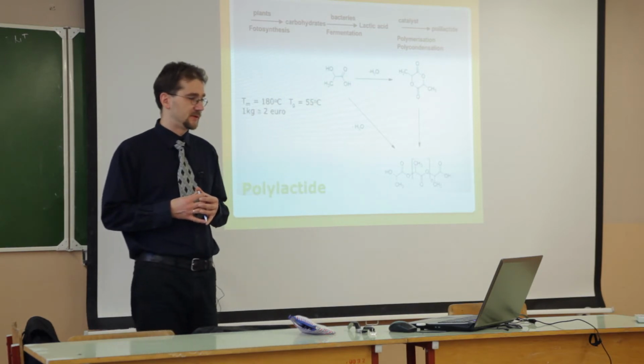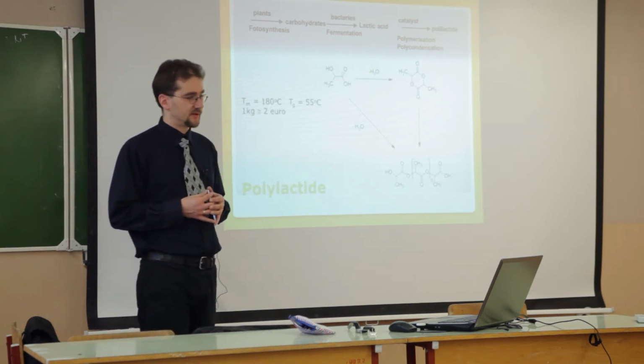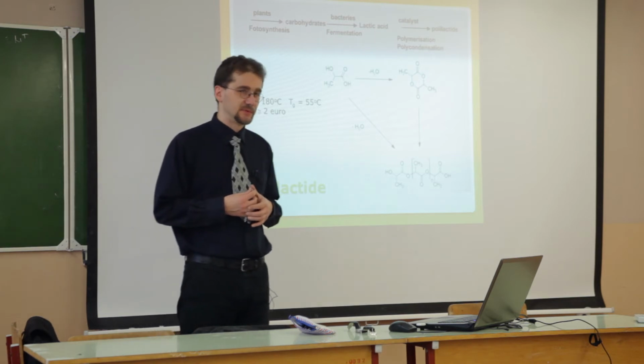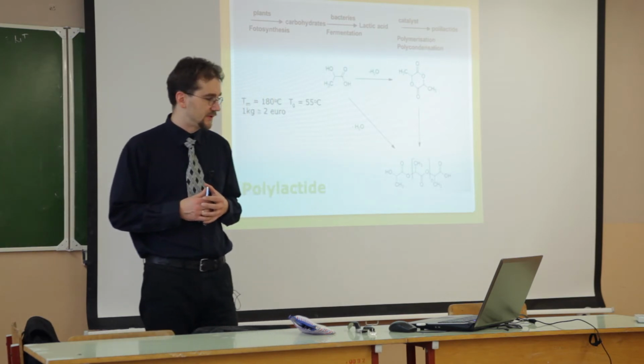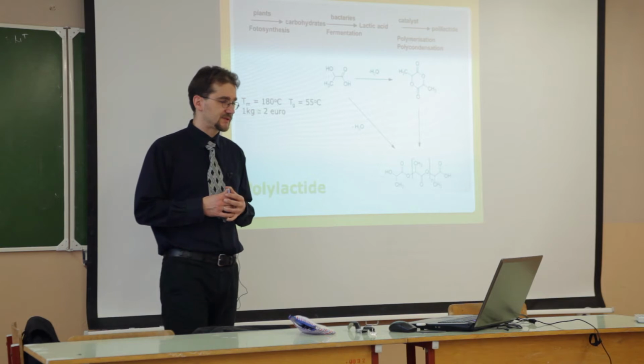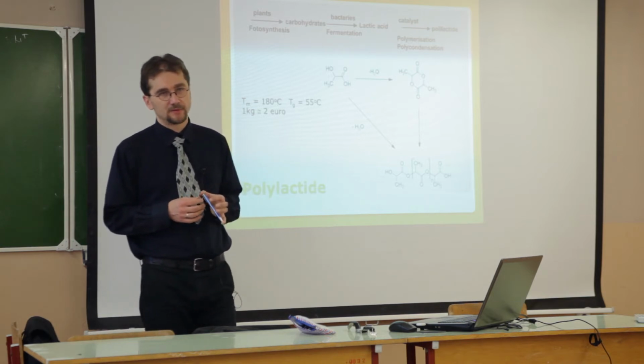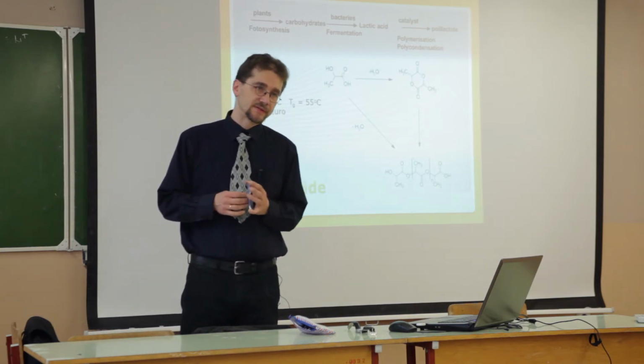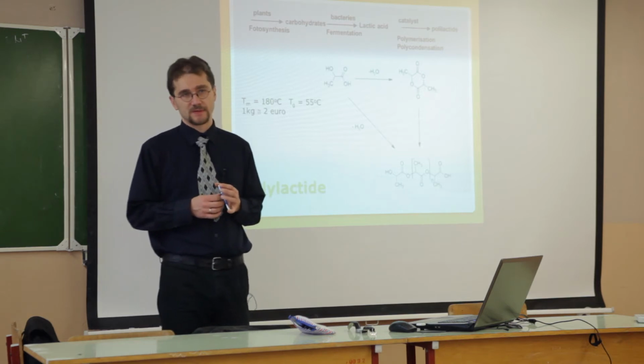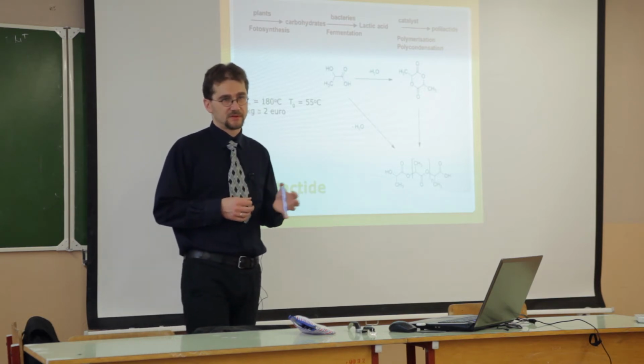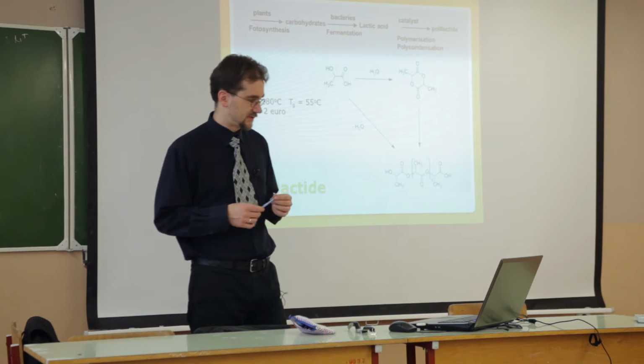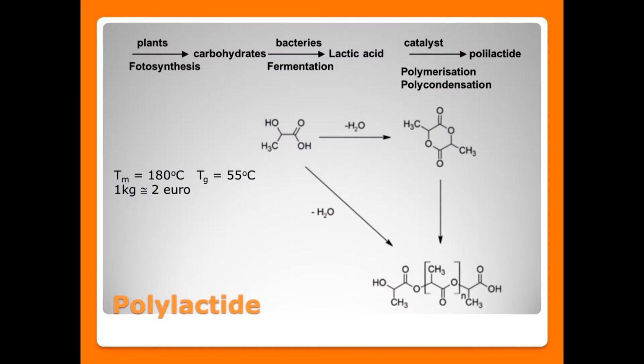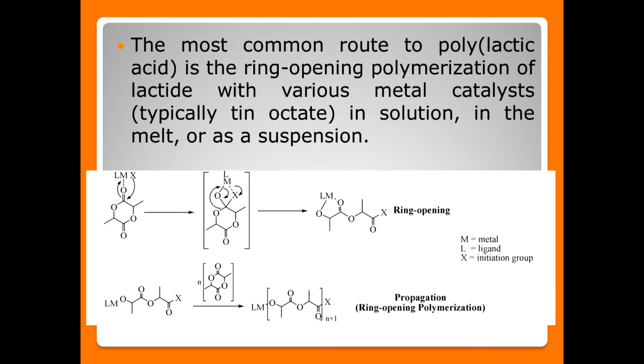Melting temperature of that polymer is 180 degrees, glass temperature about 55 degrees, and the cost per kilogram is about €2. So it is not very cheap, but it is not expensive. I mean the cost in the industrial process, which we estimate at €2 per kilogram.